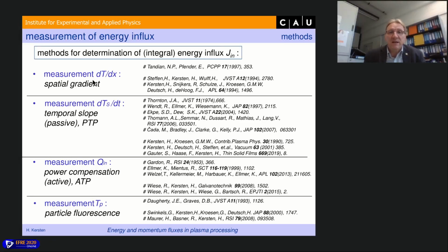One is the measurement where you just measure the spatial gradient of the temperature. For instance, if you have some thermocouples along the substrate holder or along the substrate, then you can measure the temperature at the different positions, and you can get dT/dx, so that's the spatial gradient. And from that, if you have a calibrated power, if you know the spatial gradient, you can determine the energy influx.